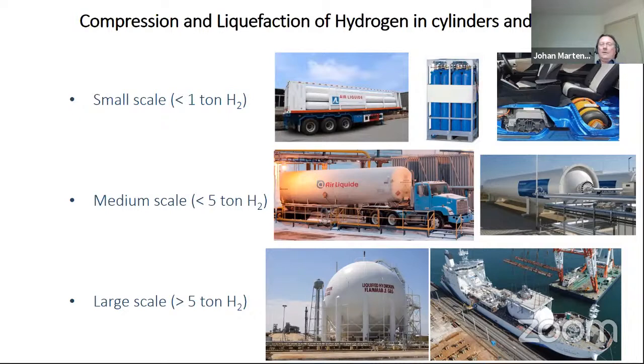The energy expenses of storing and transporting hydrogen these ways. For small scale, you have compressed cylinders. The pressures in those cylinders, it's 200 bars, 300 bars. For the tanks of trucks and cars, it goes higher. In cars, it goes even to 700 atmospheres. So very high pressures are needed to have a significant content of hydrogen in these tanks.